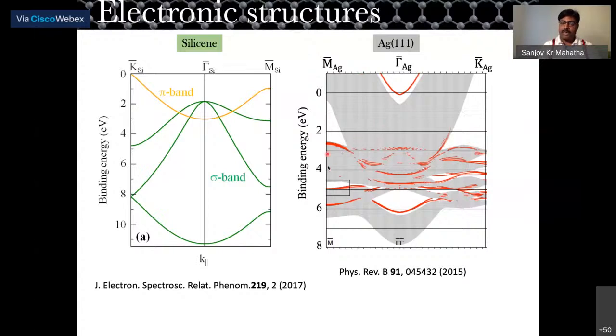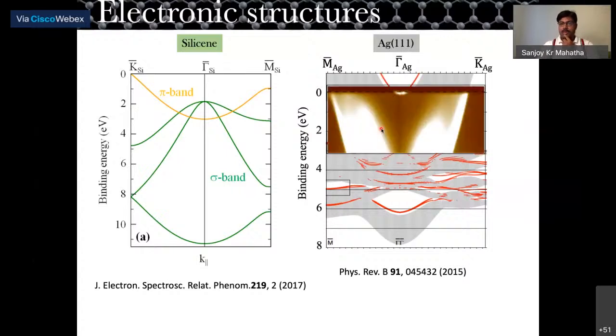Below 3 electron volt binding energy, there are strong d bands, and then there is the sp band crossing the Fermi level. So this gray plot is basically the projected bands of silver 111. And then we also have a surface state at gamma, this red one. Now if you do the experiment on silver 111, this is what we get. This is the experimental band structure from angle-resolved photoemission spectroscopy. You see this is the surface state, and these are the projected silver sp bands.